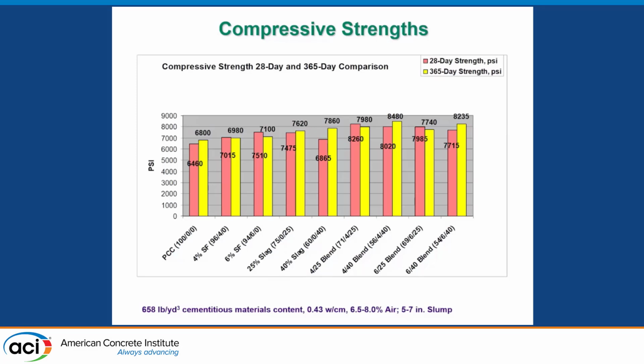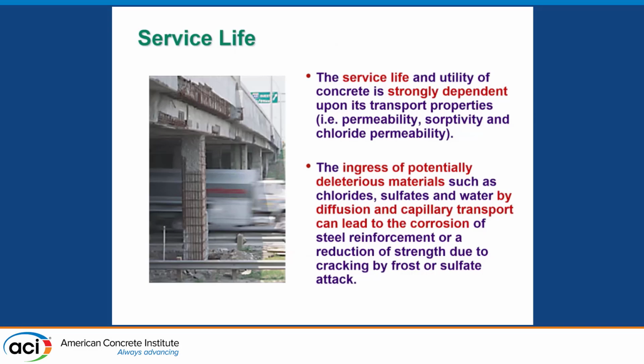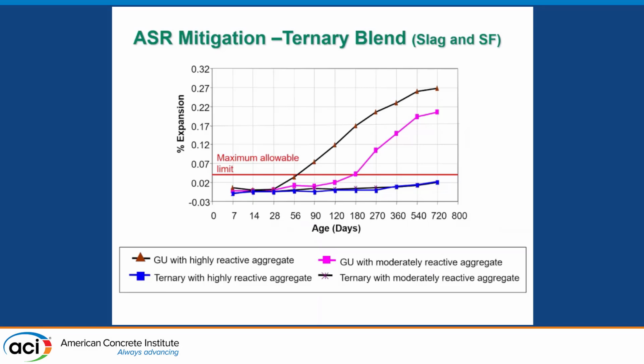If I just had the Portland cement blend, it's fine, but I believe I would have to go back and really look at the durability issues on this, and we did, which is pretty much where I'm going with this. When we looked at the service life of these particular blends, we looked at the limits. We looked at ASR mitigation because obviously that is a big concern to us, and what the allowable limits were. When you have a GU cement, it can be highly reactive when you have reactive aggregate. A GU cement is basically a Type I-II. But as I add the ternaries, I see I'm well below the maximum allowable limit.